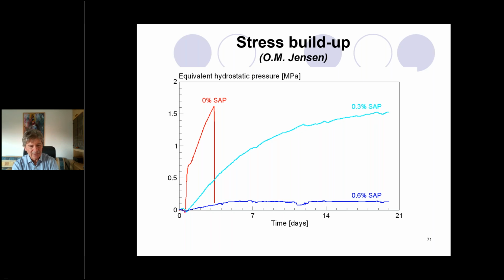If the water is used up because self-desiccation starts, then hydration stops. And then we have two parallel events: self-desiccation, the dropping of the relative humidity in the pores, and autogeneous shrinkage. This is extremely important to understand. This kind of concrete made of very low water cement ratio is extremely sensitive to curing. And only internal curing can be a good solution. External, conventional curing methods do not work perfectly.